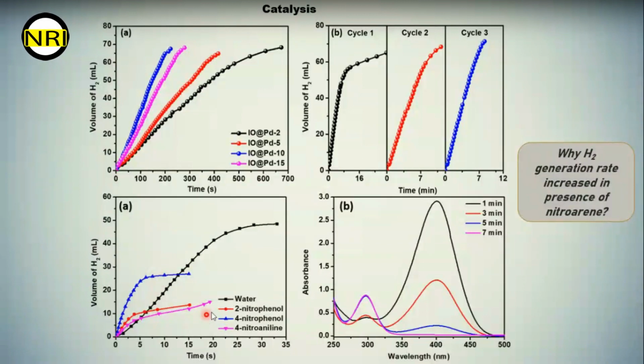And this is the corresponding nitrophenol reduction UV-visible graph. Generally 4-nitrophenol will give you a peak at 320 nanometer, but if we add some reducing agent, then this peak will be shifted to 400 nanometer because of the formation of 4-nitrophenolate. And in presence of the catalyst, this 4-nitrophenolate peak will decrease, and a new peak will appear at 300 nanometer. This is the formation of 4-aminophenol.